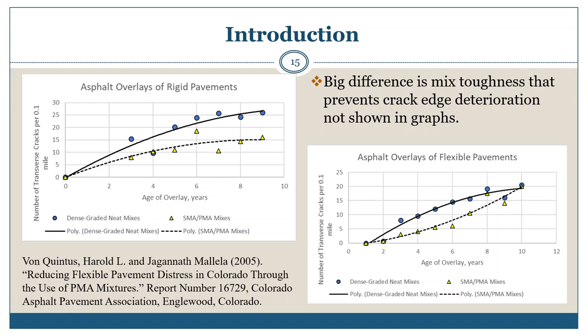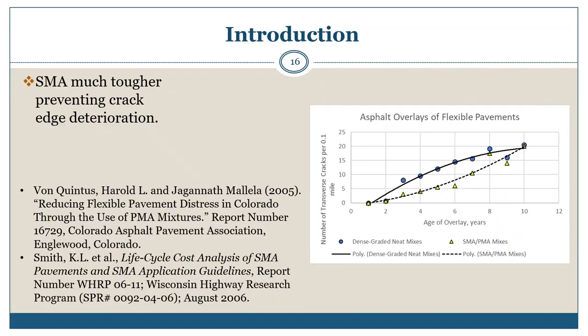A more important observation, however, that is not illustrated in these 2 graphs is the crack deterioration between SMA mixes and conventional dense graded mixes when cracks do occur. The difference in crack deterioration between the 2 mixtures will be illustrated on the next slide. SMA is considered a much tougher mixture, preventing crack edge deterioration.